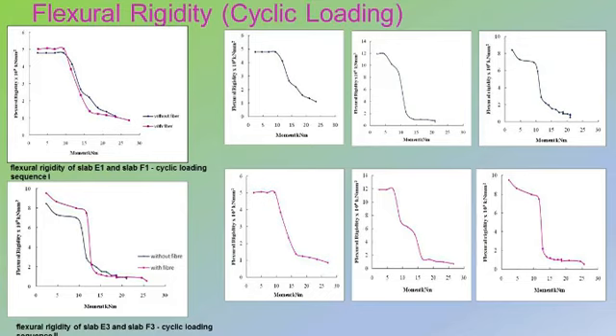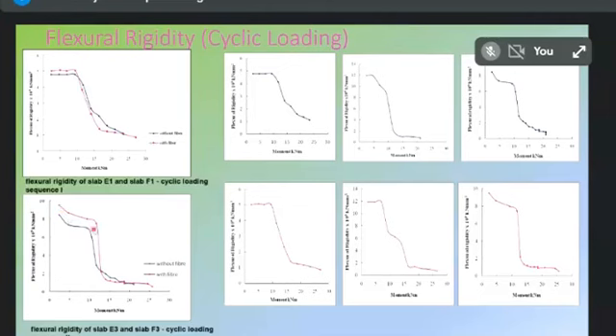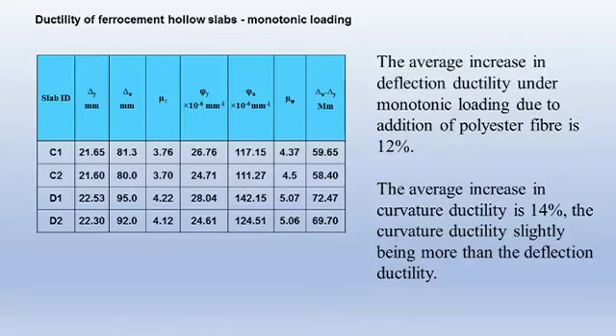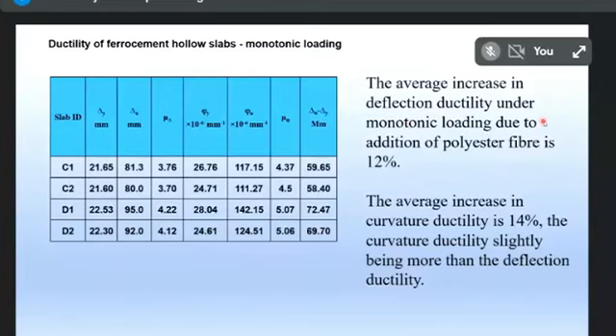The stiffness curve indicates the decline in stiffness as the moment increases. Here for the fiber enriched slabs, the stiffness was higher when compared to slabs without fiber. And ductility is a very important factor to be studied. The average increase in deflection ductility under monotonic loading due to addition of polyester fiber is 12%.